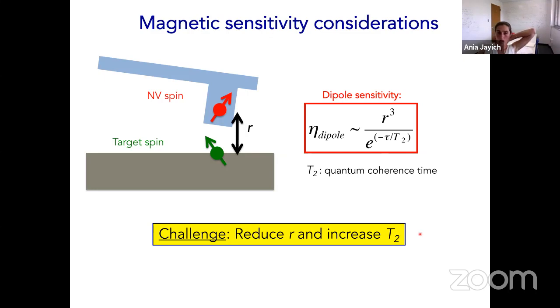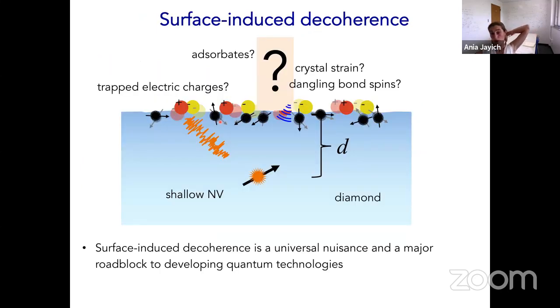However, that's a hard challenge because generally as you bring an NV center close to a surface, as you make r small, this T2 time gets smaller. Why is that? There's a variety of reasons. They're not all totally clear, but the surface is basically uncontrolled. The diamond has this nice pristine diamond lattice. It's very protective of the quantum coherence, but the surface is uncontrolled. There can be trapped charges and trapped spins. There could be strain fluctuation. There can be dangling bonds, and those can reduce the coherence. And this surface-induced decoherence, I'd say, is a universal nuisance.